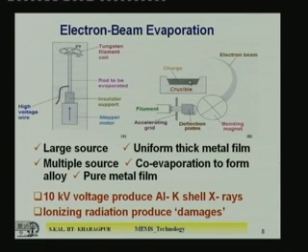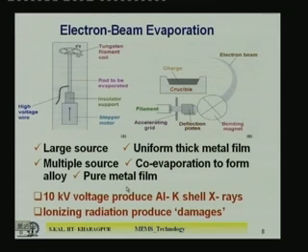If the focused beam is scanned over the surface, only the surface melts and evaporation takes place from there. Since the complete material does not melt, there is almost no contamination from the crucible — only the surface is melted by the kinetic energy of the electron beam. This is a major advantage. You can also use a large source material, and the result is a uniform thick metal film with good purity compared to the earlier two techniques.